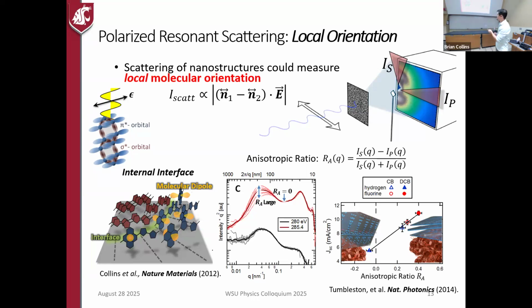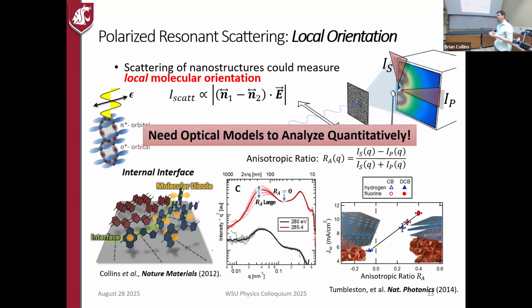So if you're zoomed in to, say, a domain, maybe there's a domain of red molecules, and it's surrounded by these blue molecules, you have this molecular orientation that is maybe resonant with the polarization, and this one that is not. And so that will change your contrast in one direction versus scattering in the other direction, and give you these anisotropic scattering patterns. That's what we call the S and P polarized scattering. So the question is, can we be more quantitative about this, right? This was cool, got a lot of press and stuff like that. Can we actually learn more quantitatively about this?